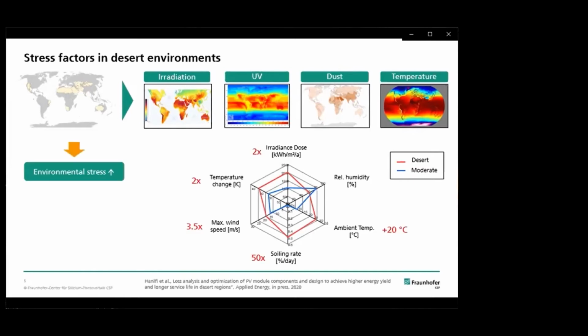And what you will find is that especially the irradiance dose will be increased, which is positive in most of the ways, but also it leads to increased temperatures of your PV modules. On the other hand, you have an average increased ambient temperature, and you will also have a soiling rate which is much higher, up to 50 times depending on the location where you are. Wind speeds could be much higher in some deserts, and also the temperature change between day and night could be increased. And this environmental stress also leads to necessarily more O&M and less lifetime of the PV modules, because of different degradation modes and performance issues, which will be shown on the next slide.